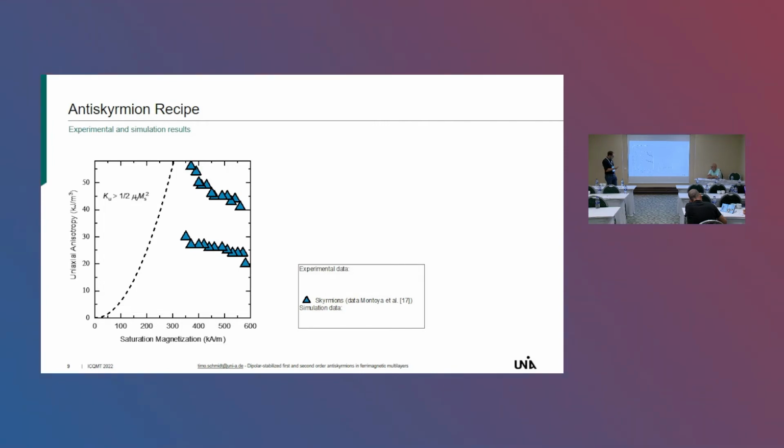And if we add our own, then we have here these coexisting antiskyrmions and skyrmions in violet, the samples which only had skyrmions in the blue squares, and also in-plane domains, where the Ku value is just too low to get these out-of-plane things.